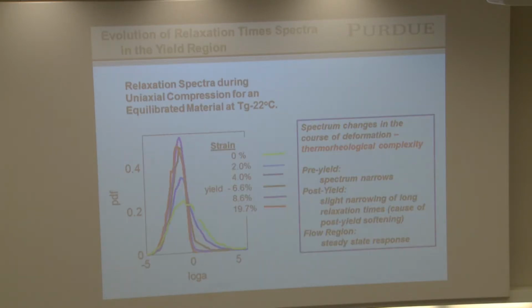And so the origin of this is the change in the width of the spectra during deformation. And I show that over here. This is what happens to the relaxation spectra of the material as deformation occurs. So we start off with the green curve when it's undeformed. As the material goes forward, we see the narrowing of the spectra, and then again we see it narrowing even more here. So we have a definite prediction of what happens.